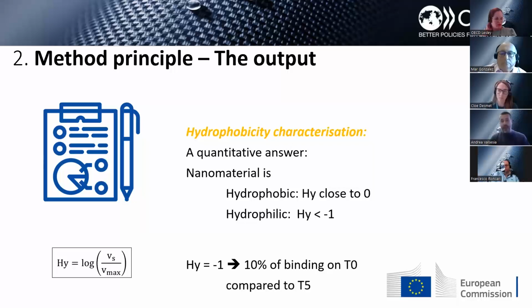So we defined, just to give an idea, that a material is hydrophobic when the H index is close to 0. If only, for example, 10% of particles are binding at T0 on the hydrophobic collector compared to the maximum velocity, the hydrophobicity index would be -1. So we can define that a material with a hydrophobicity index lower than -1 is a hydrophilic material. We also have a scale, a degree, that can define the degree of hydrophobicity of the nanomaterials we are characterizing. Next slide.